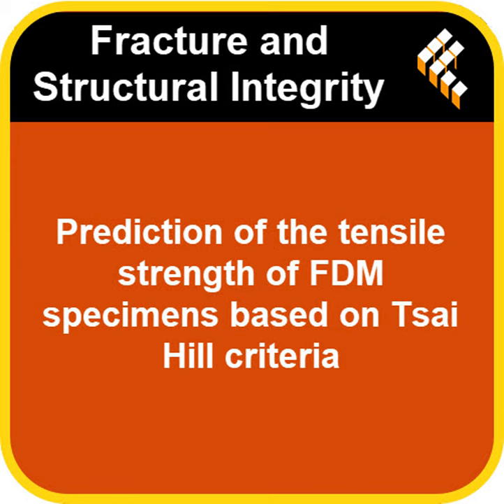Oh, okay. So strongest along the grain, the shell doesn't add much to peak strength there. Hmm. What about turning the grain sideways, when the lines were at 90 degrees to the pull? Yeah, the 90-degree case. So when those internal filaments were at a right angle to the pulling force, those parts were still stronger than the 45-degree ones we'll get to.